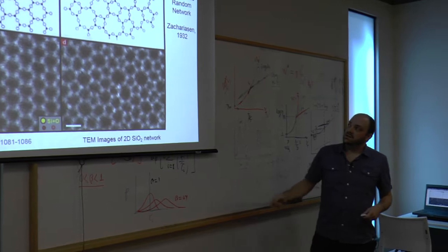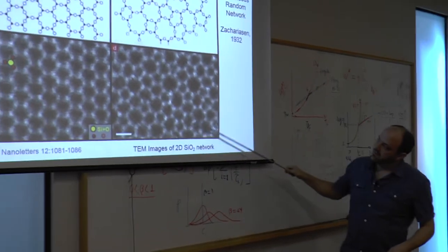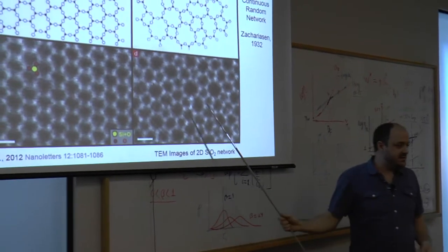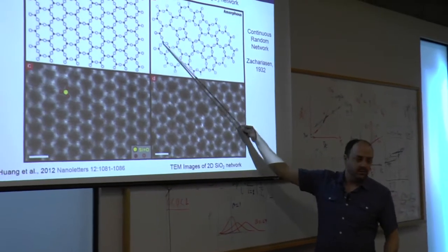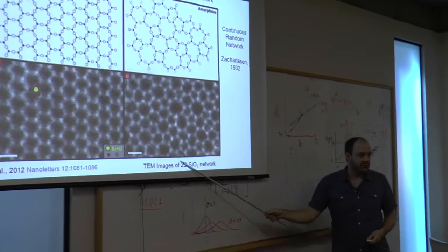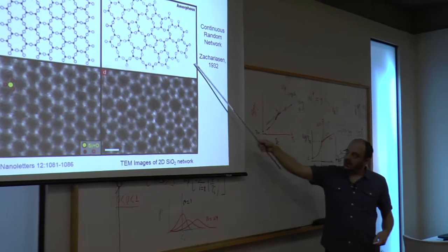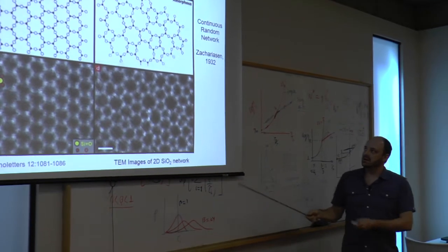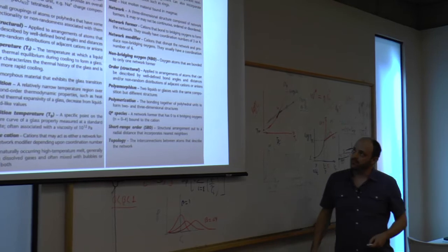And the biggest of these is that in this image, if you look closely, and I stared at this for hours, you don't get any 4-member rings, and you don't get any 3-member rings. So it's very close, but there are some things to be cautious about.